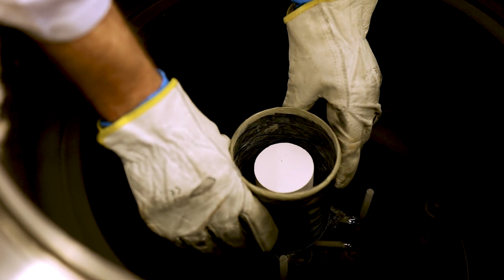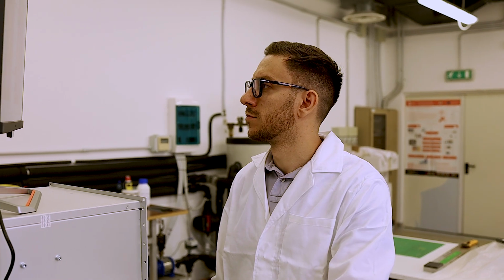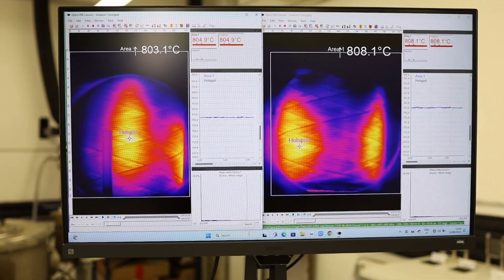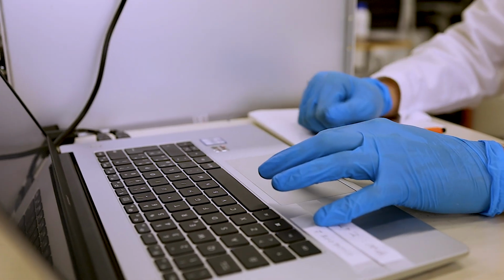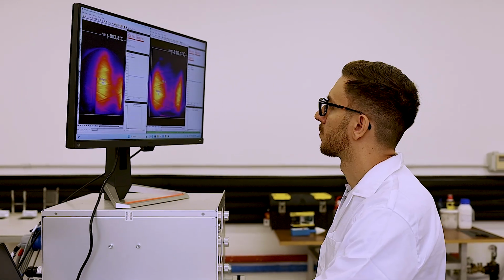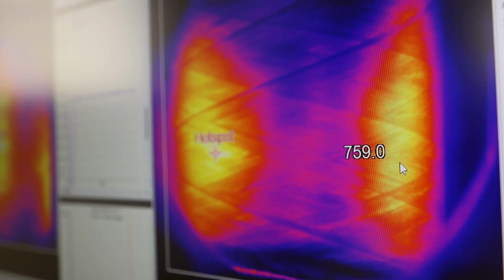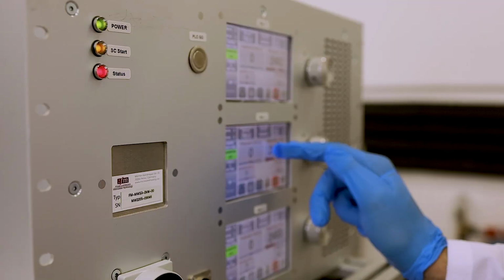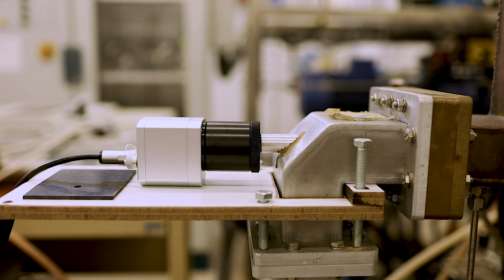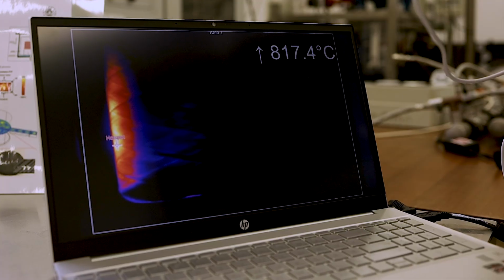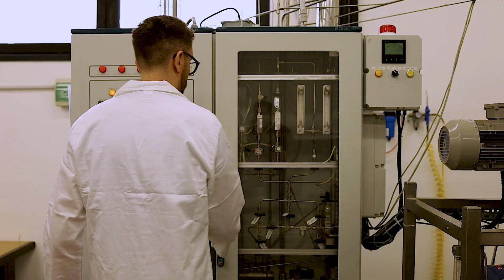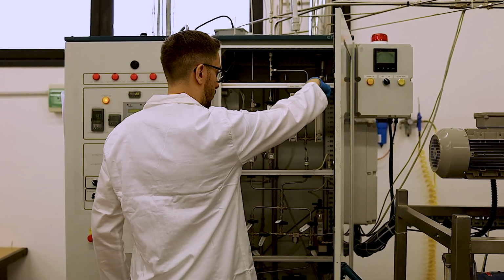One of the major challenges has always been the control and tailoring of a well-defined heating pattern on preforms. The replacement of magnetrons with the latest solid-state sources that, thanks to the fast and precise control of the frequency, will allow a finer tuning of the operating parameters to achieve a higher quality product. The University of Pisa defined the best operating conditions for the silicon carbide matrix densification process of the preforms using the frequency tunability of the microwave solid-state sources system. This process was guided by the National Research Council of Italy, developing electromagnetic thermal models, thus maximizing both the energy and the chemical process efficiency.